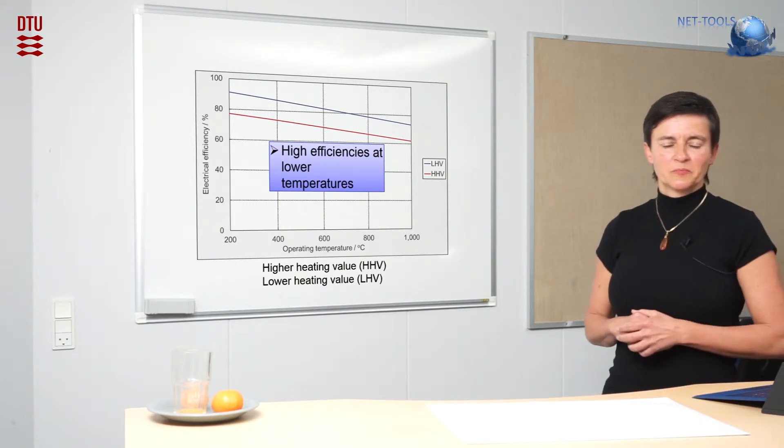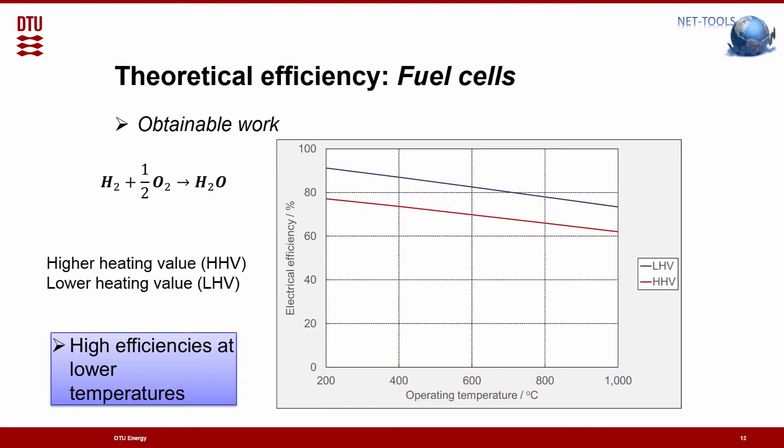So the take-home message is that fuel cells already deliver high electrical efficiencies at lower temperatures. In particular compared to Carnot efficiencies, this is an advantage because you don't need to go to very high temperatures and you can use cheaper system materials.